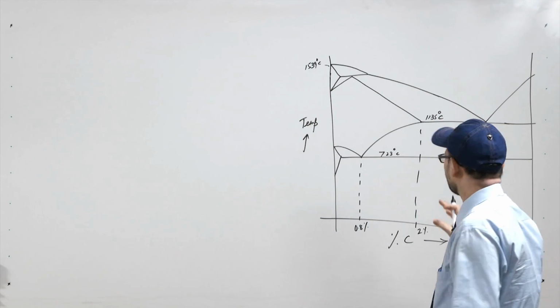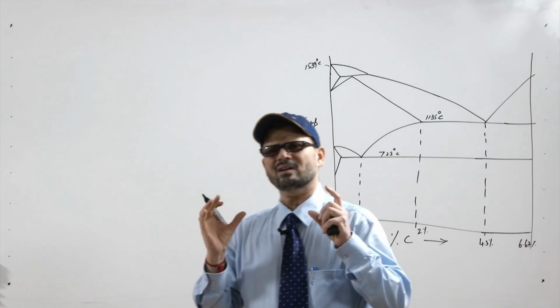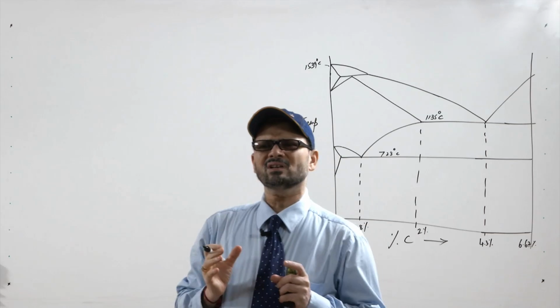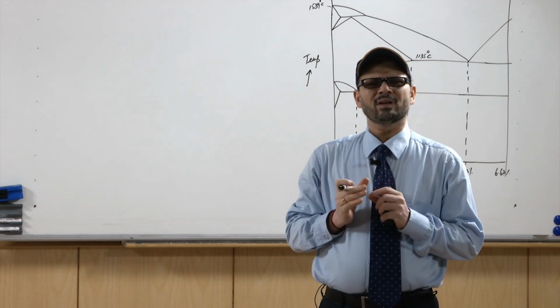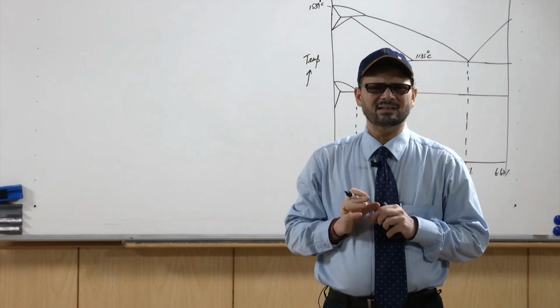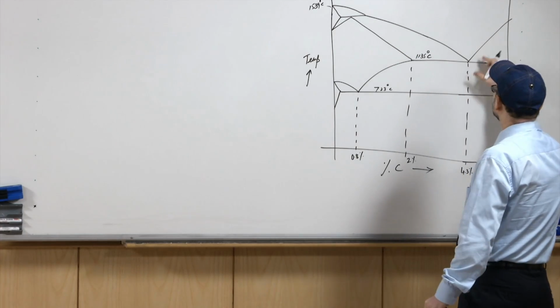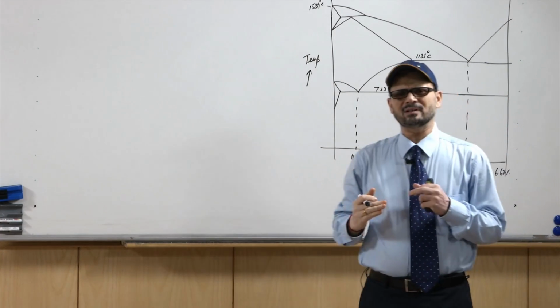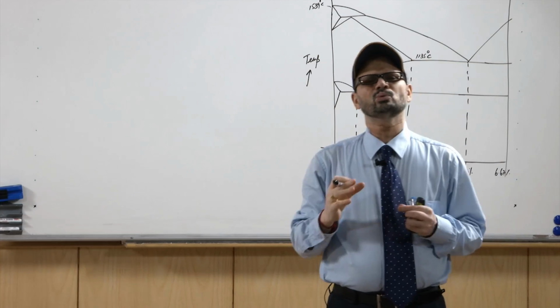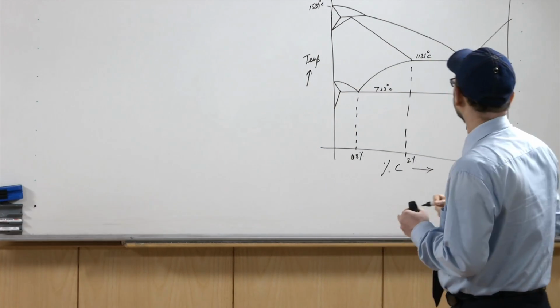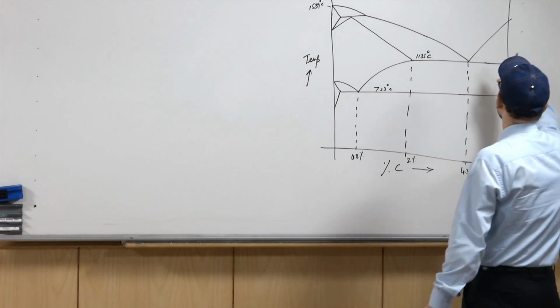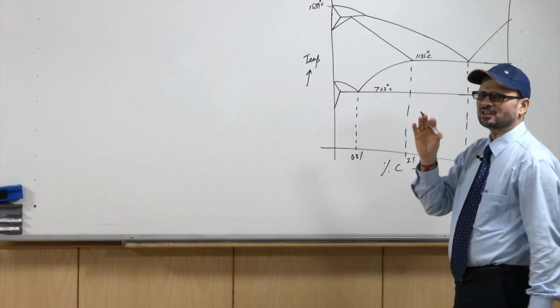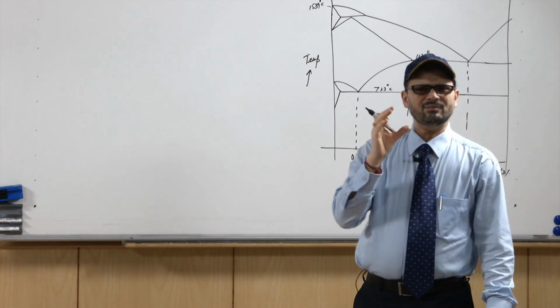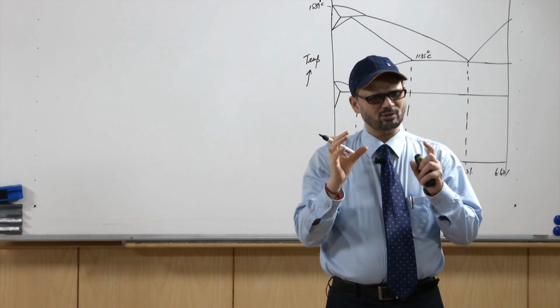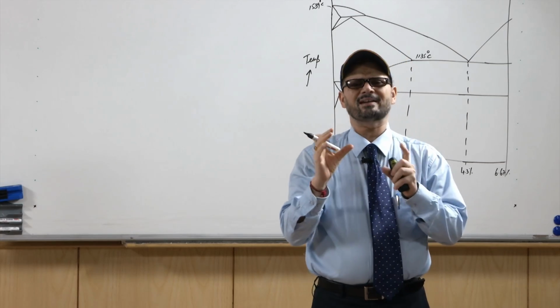Now, in the case of cast iron, the composition as well as the cooling is adjusted in such a manner that when it cools, this excess carbon is changed to graphite. So, that is free carbon, and in that case the carbon is not in the form of Fe3C. Now, it depends upon the cooling rate and composition.